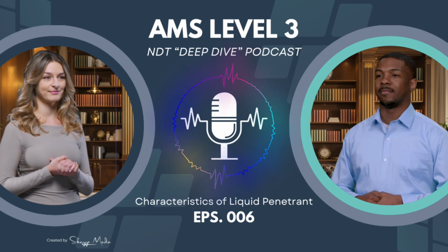Right. And what about volatility? Does it matter if the liquid evaporates easily? You might think faster drying would be a good thing. Actually, for the penetrant itself, it's the opposite. Low volatility is really important for several reasons. First, simple economics. Less evaporation means less product lost. Second, safety. Fewer flammable or potentially harmful vapors hanging around the test area. That's a big one. Definitely.